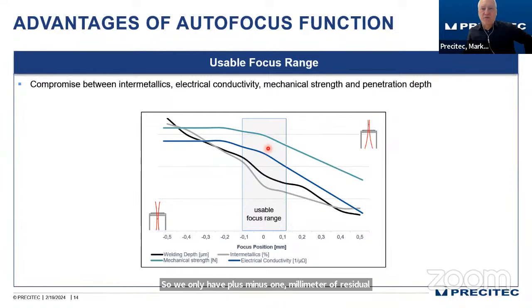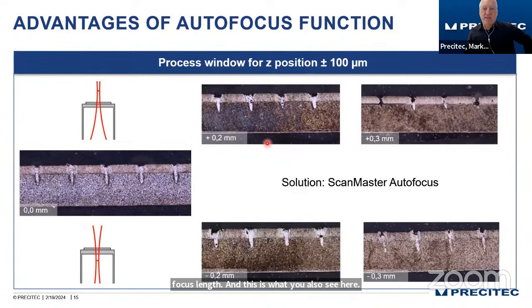And this is what you also see here in the cross sections. So if you exceed these limits, plus minus 0.3, you see that we directly run out of the limits, and the weld performance is not good. I have to admit these cross sections and these welds haven't been performed yet with the Canunda from K-Labs. We will do that, and we will provide a new slide in the near future on that specific application with the new beam shaping solution.